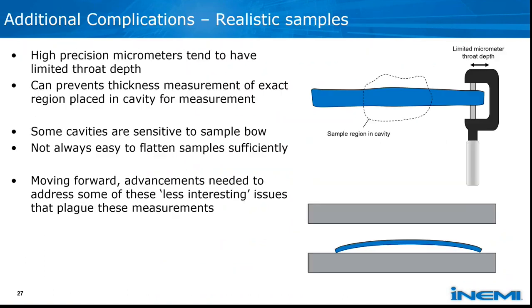There's a few additional complications when we looked at the realistic samples that'll be talked about in task 4. Most labs use high precision micrometers, which tend to have a relatively limited throat depth. So if you look at the picture on the right, most of the time you have to measure the samples somewhere near the edge. In a lot of the measurement techniques, the fields used for extracting the dielectric constant are in a region you can't physically measure with a common micrometer. Drop gauges can improve on this, but they also have limitations. So assessing thickness turns out to be an important place where we might make improvements in the future.